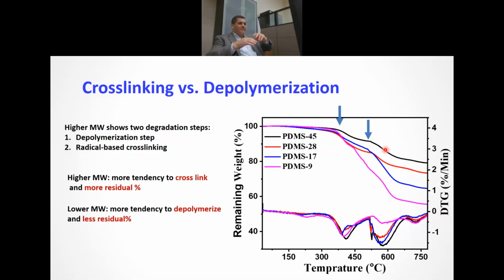you form cross-links. After you degrade, the heat will form additional cross-links, and eventually it will form a silicon carbide or a silicon oxycarbide layer. And we actually confirmed this with the TGA-FTIR. In the next slide, you'll see it. While the depolymerization one will tend to have more carbon, and this is what happens in the lower molecular weight one, the pink one. This is why the residue for the high molecular weight one is more than the residue for the low molecular weight one, because of this silicon oxycarbide. Thermally, it acts as a shield to prevent further degradation of the material.